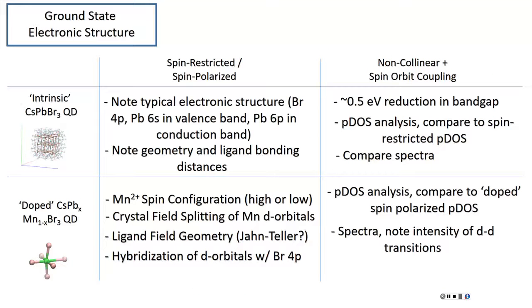So I just put up bullet points of what I planned to mention in my paper. I didn't put any figures because it would take a long time to go through them all. And I have it laid out as a 2x2 because for 2 quantum dots, we do 2 different sets of calculations for each one. So if we're doing geometry optimization, we do spin restricted calculations for the intrinsic quantum dot, and we do spin polarized for the doped quantum dot because we're dealing with transition metals, which can have a variety of different spin configurations. So you have to do spin polarized to get the correct electron configuration.